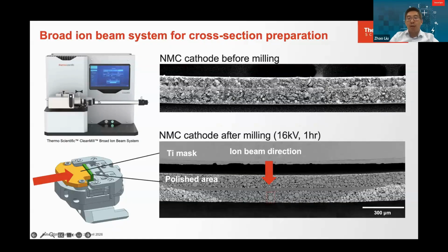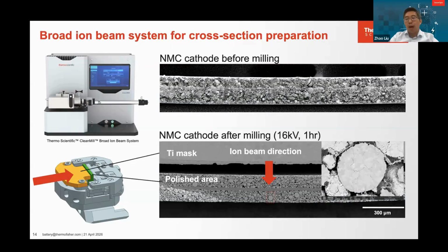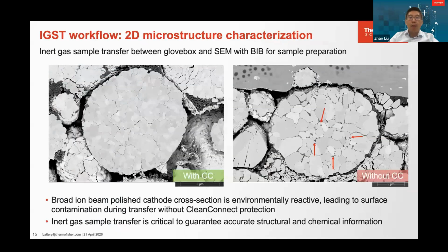On the right shows the SEM imaging overview of how the cross-section is prepared. As you can see, after the broad ion milling process, you will have a very large, sub-millimeter range cross-section well prepared that is able to do the microstructure analysis. You can also zoom in to find the quality of the preparation is really good, so a lot of details are able to be captured for your SEM characterization in this way. Again, we can also compare the sample transfer with or without Clean Connect.